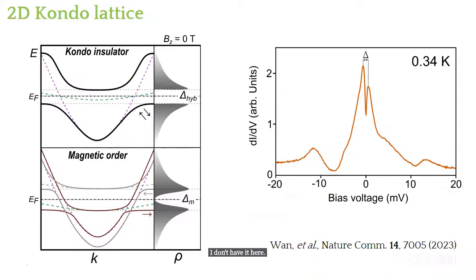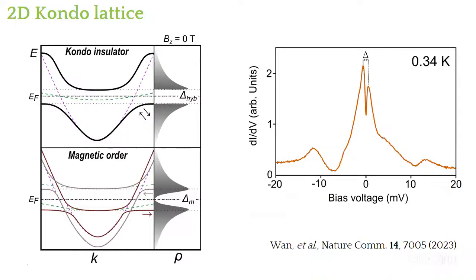What's the bandwidth of that? I don't know, 100 milli-electron volts or so. It's less, 30 or 40 at least. But a key difference from ARPES is that those are bulk experiments, and the stacking of the charge density wave matters a lot, because there is hybridization between bilayers, and that you don't have here. Why should there be a difference? Because of the stacking of the charge density wave, versus the monolayer.